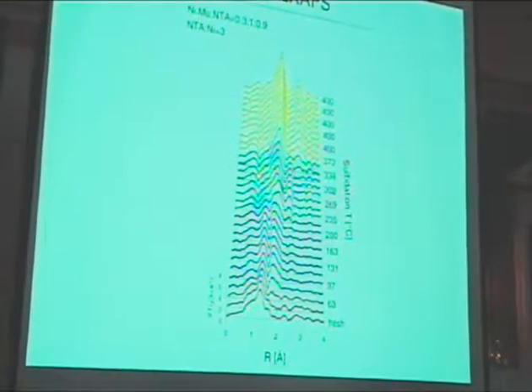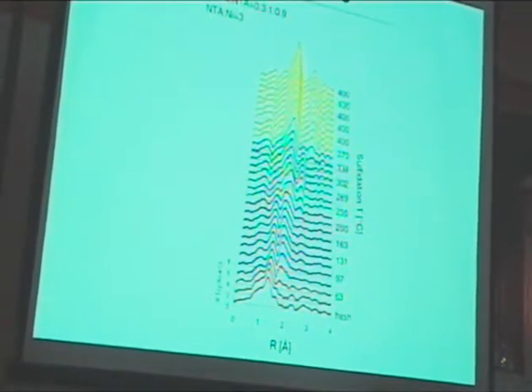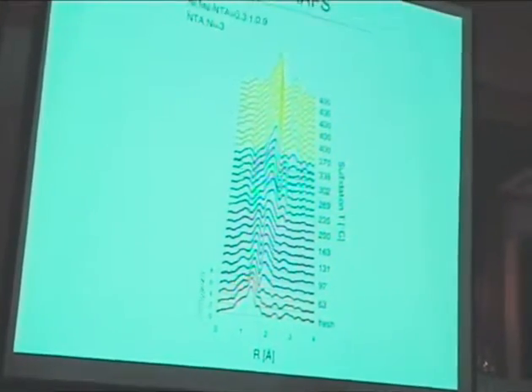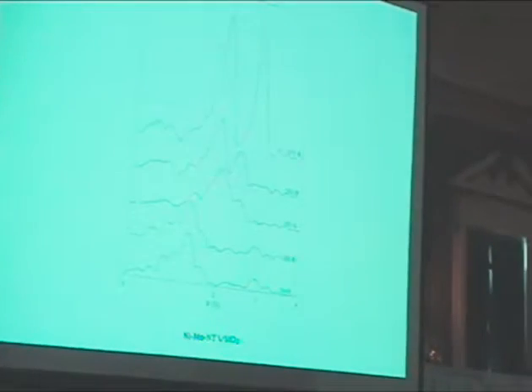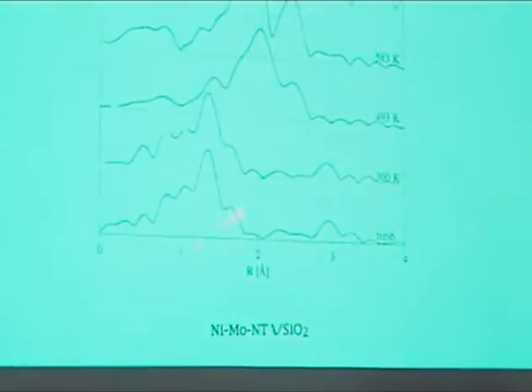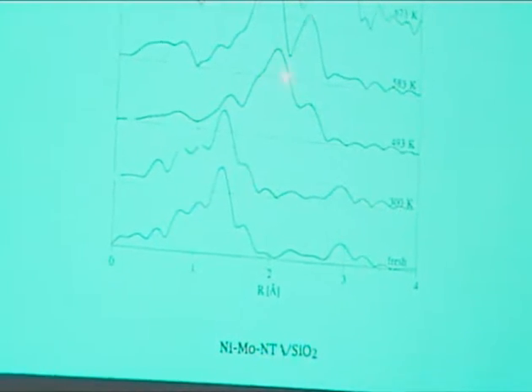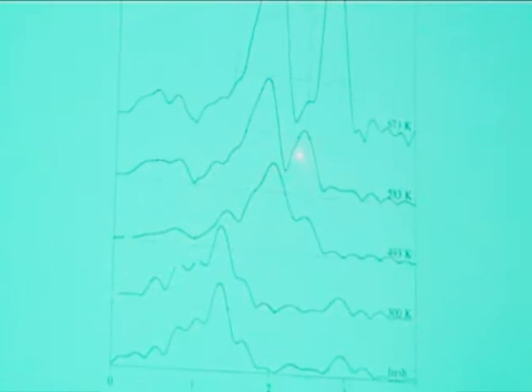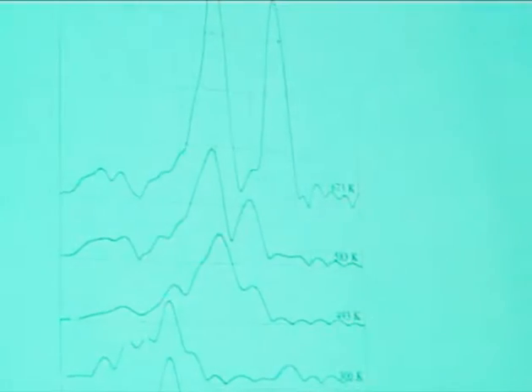So we know at the end we have MoS2, and of course we expect it, but we definitely have 2 intermediate phases. And the question is what are they? This is one of the ways to distinguish them, and this is structural information. If you just take a few of those spectra, you see originally we are in the low region, then later peaks come in, and we have an intermediate state with a peak here, and then eventually we have a peak at around 2.8 or something, and then here.